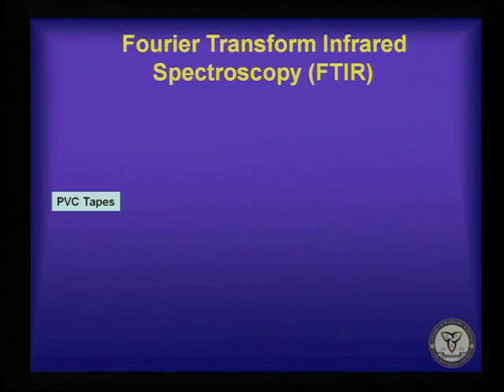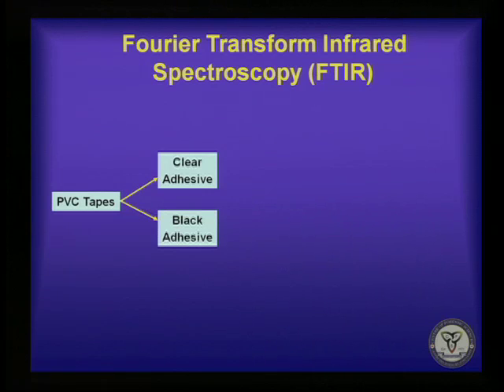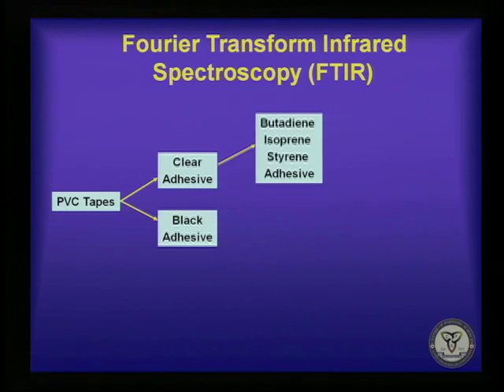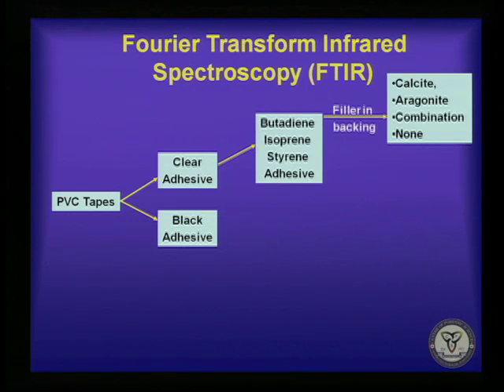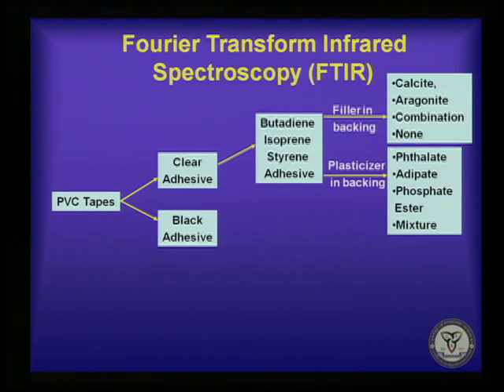I'll first go through the different techniques, and then at the end I'll go through the results that we obtained. So for the polyvinyl chloride-backed tapes, they were first divided into tapes with clear adhesives and black adhesives. The adhesives were generally butadiene isoprene styrene, and they had a combination of fillers, calcite, aragonite, a combination of the two, or none seen by IR. And they also had plasticizers, either phthalates, adipates. Two samples had phosphate esters, and some of the samples had mixtures.